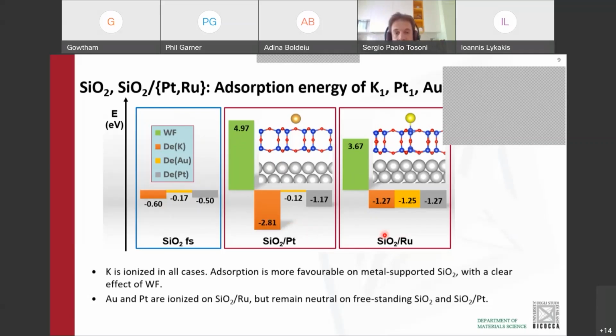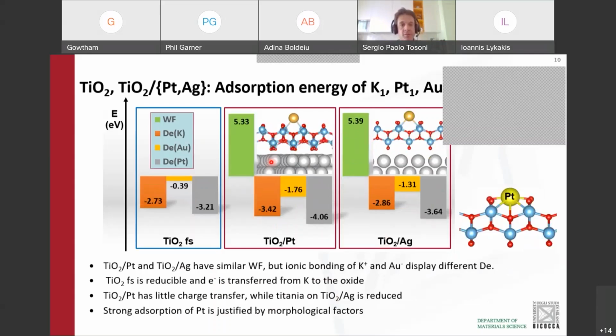silica on ruthenium. Gold, in the case of SiO2 supported on Pt, is still adsorbed as a neutral atom, and as you can see, it's very weakly bound. Things change on ruthenium, where gold becomes gold minus, thanks to the smaller work function of the system. And also platinum is ionized on this SiO2 on ruthenium system, but remains neutral on silica supported on platinum.